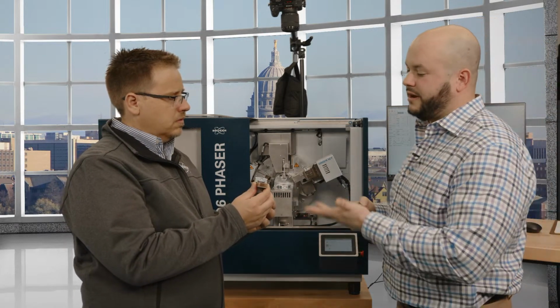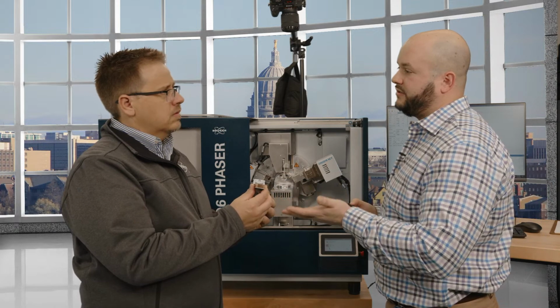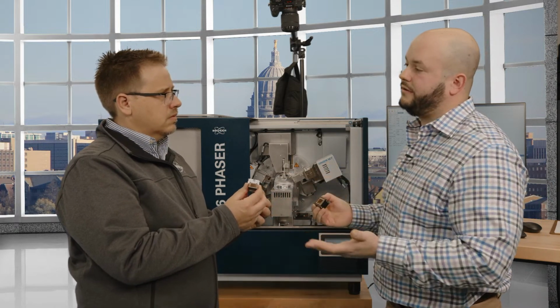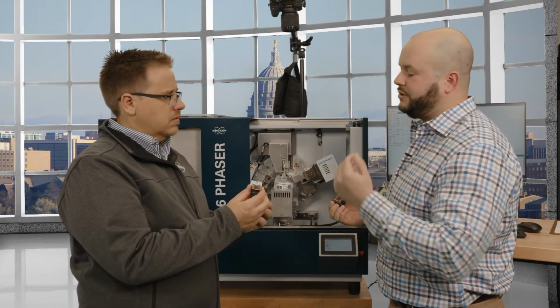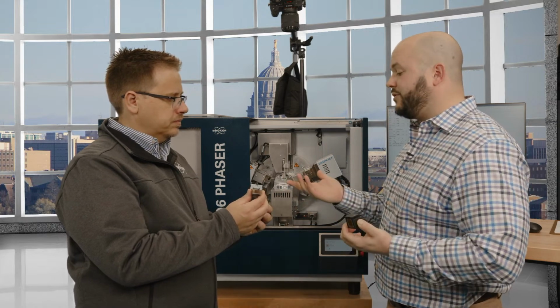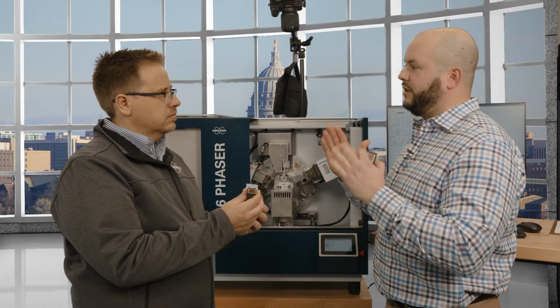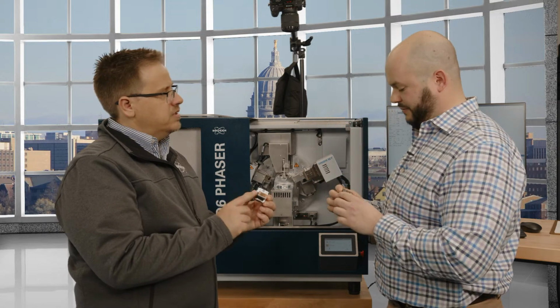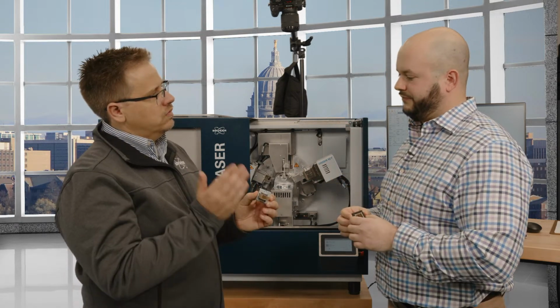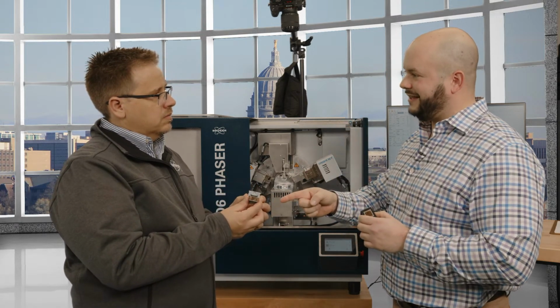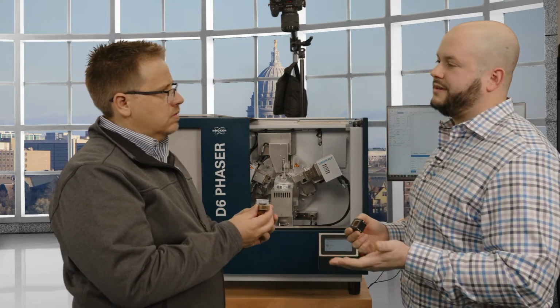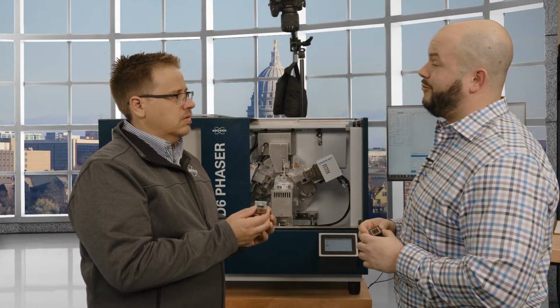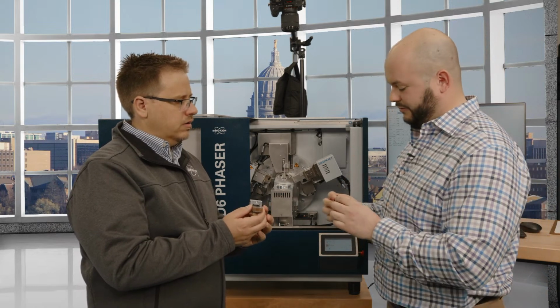And that would be used for any 0D measurements like grazing incidence diffraction. You'll see in texture today we're going to be doing 0D phi scans, so that's useful for that. It can be used in residual stress too if you want to eliminate any peak broadening. And you do have different sizes of these for balancing resolution versus intensity. That's right. So we're going for all intensity today with the 0.4. We also have a 0.2 degree and I believe a 0.1, but I would have to double check that.